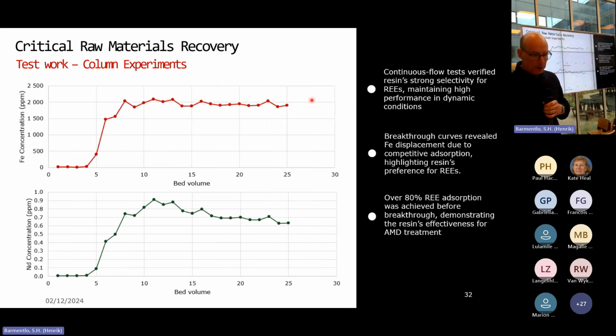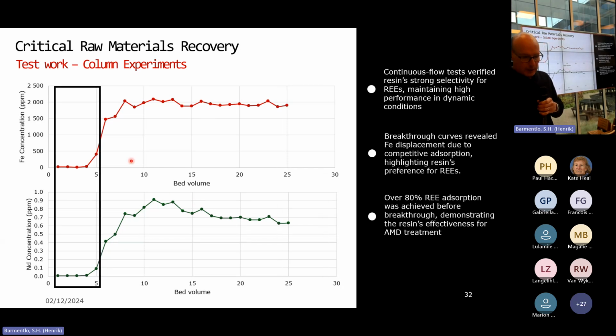So we did this with our two primary compounds. We said, let's have a look at neodymium and let's have a look at iron. And from 4 or 5 bed volumes, we start seeing a little bit of breakthrough, and then it comes out at the end. And that's what you're seeing over there, where we see the breakthrough starting to happen. So in both instances, it's there. We had about 80% rare earth absorption before breakthrough. So what that's telling us is that this technology is effective. It can actually work. But what it's also showing you is that the iron comes into your resins too.